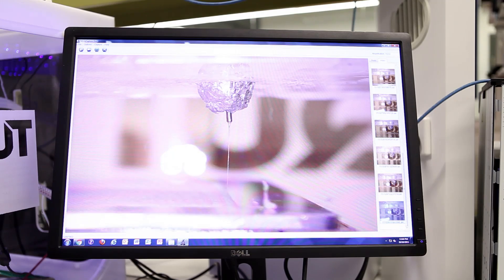We use a polymer very extensively in our group called polycaprolactone. This is a polymer that's resorbable, which means that over many months it dissolves. If you imagine we create that into a 3D structure and we implant that into the human body, that 3D structure starts to dissolve over time and the patient's own bone tissue can grow into that structure. Then it dissolves a bit more and the patient's tissue grows even more, and eventually you end up with a regenerated defect site.